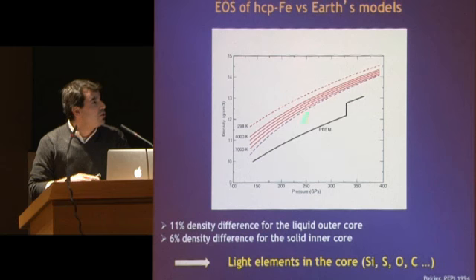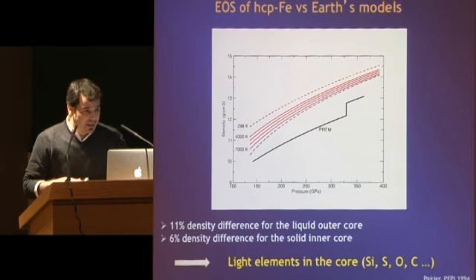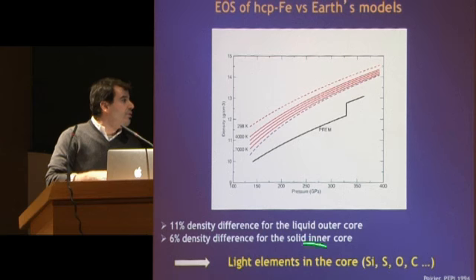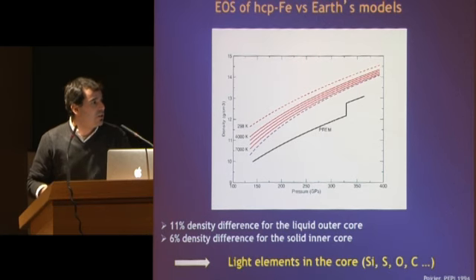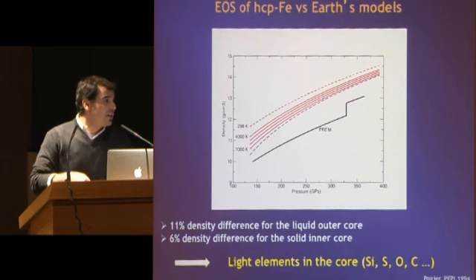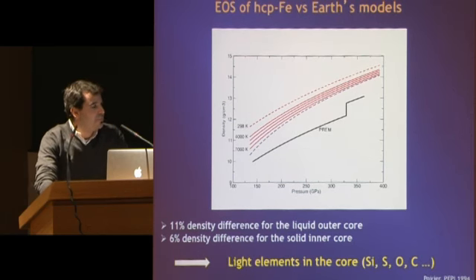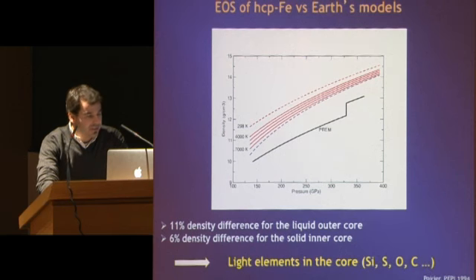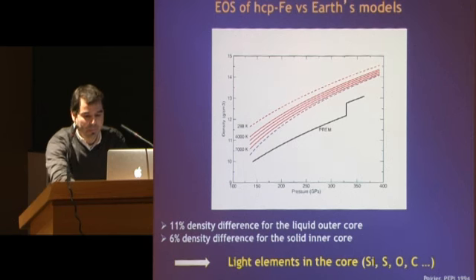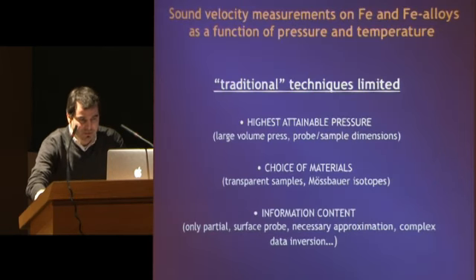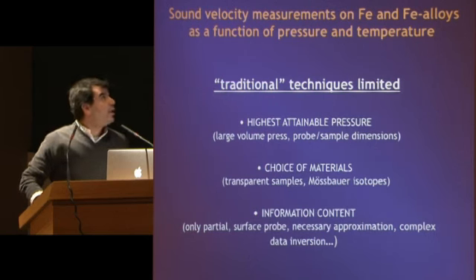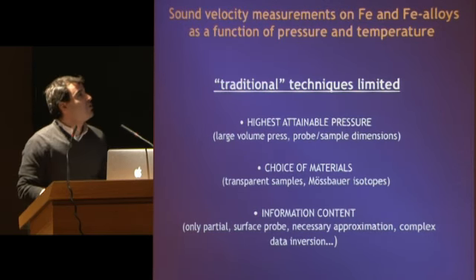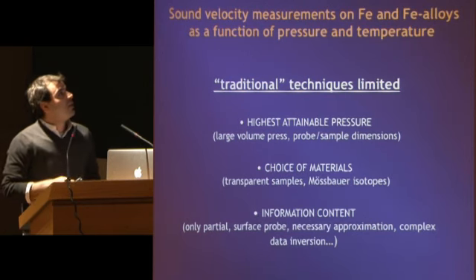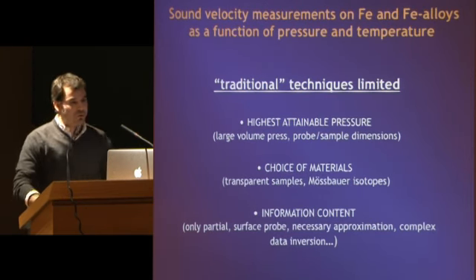So this observation provides a direct and quite compelling argument for the presence of a light element alloyed with iron in the core. And following Poirier, for example, we can include as most likely candidates silicon, sulfur, oxygen, and carbon. So it becomes evident the logic of performing sound velocity measurements on iron and iron alloys as a function of pressure and temperature.